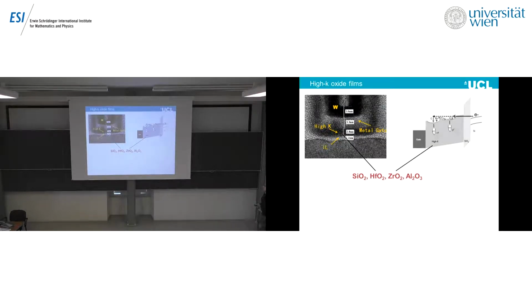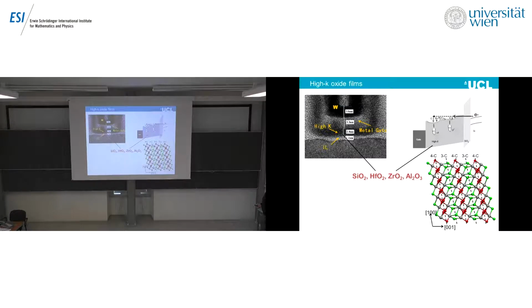At the same time, very convenient materials came into production. In the microelectronics industry, two materials became very useful, hafnia and zirconia. Hafnia has a monoclinic phase as its stable phase, which has 4- and 3-coordinated oxygens, and it has a relatively high dielectric constant, about 25, compared to previous materials like magnesium oxide or alkali halides. Therefore, one could expect that some polaron trapping could happen in these materials.